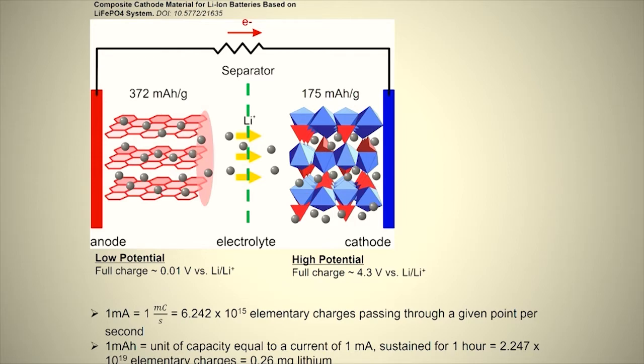But the lithium ions, this is showing discharge. So lithium ions moving from the anode back to the cathode, where they get incorporated into this crystal matrix rather than forming lithium metal. So this is the main distinction between a lithium ion cell and a primary cell or a lithium metal battery, like a coin cell. There should be no lithium metal in a properly functioning lithium-ion battery. You get lithium ions, you get lithium atoms, but no bulk lithium metal. Samsung Galaxy Note 7 did get some lithium metal, and that was kind of catastrophic. So they short-circuited. Lithium is quite reactive.